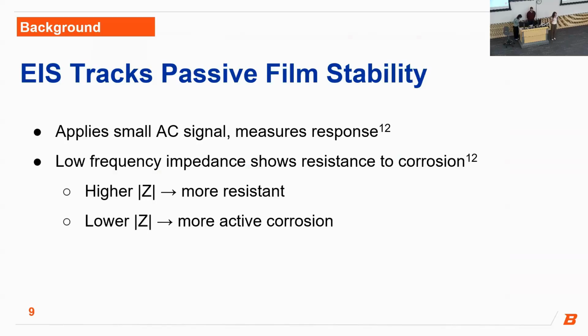So in order to analyze this, we use electrochemical testing. Specifically, we use EIS, or electrochemical impedance spectroscopy. What it does is it applies a small AC signal and it measures the response. And if you look at the low frequency impedance, you can decide how the material will be able to resist corrosion, where a higher impedance is more corrosion resistant and a lower impedance is more likely to corrode.